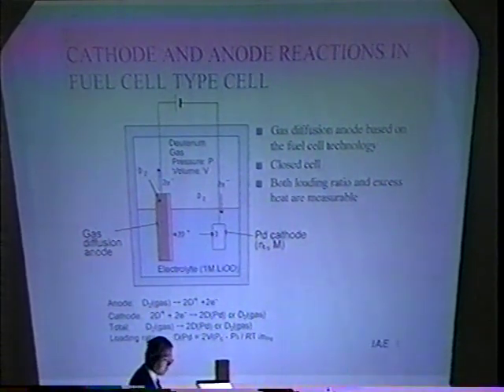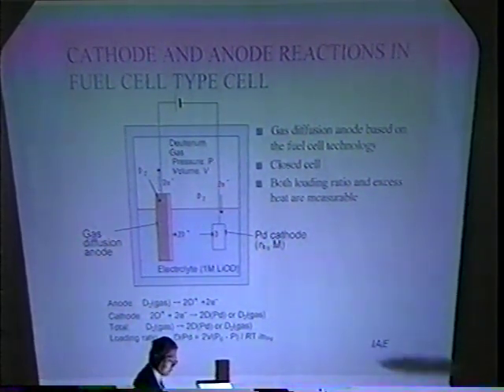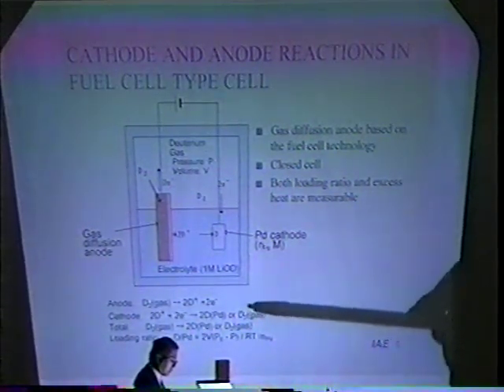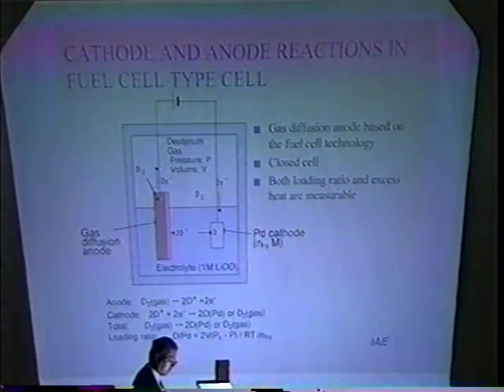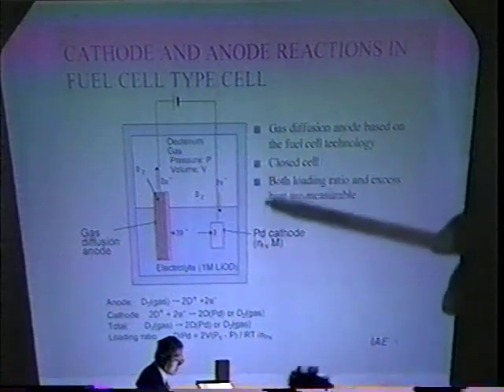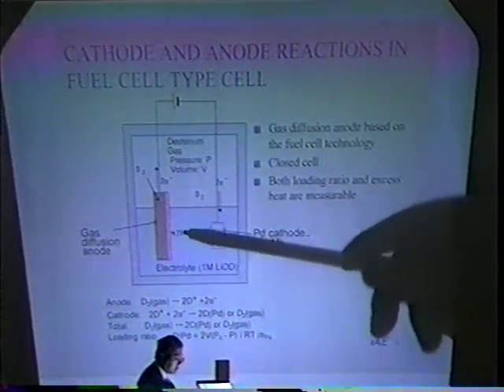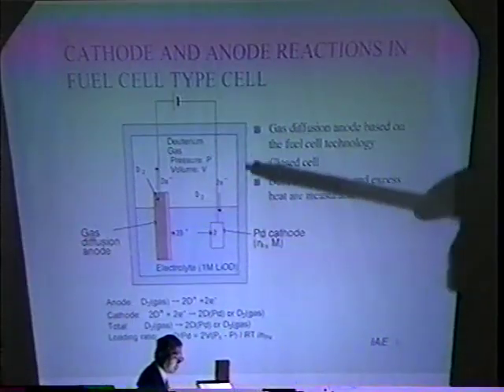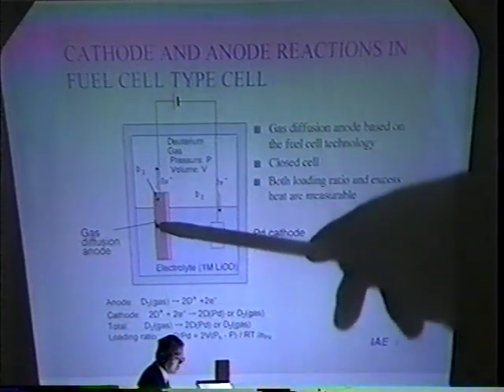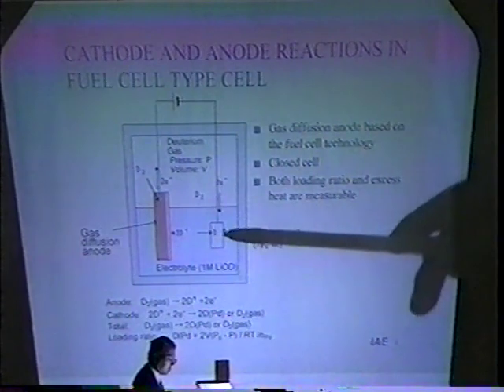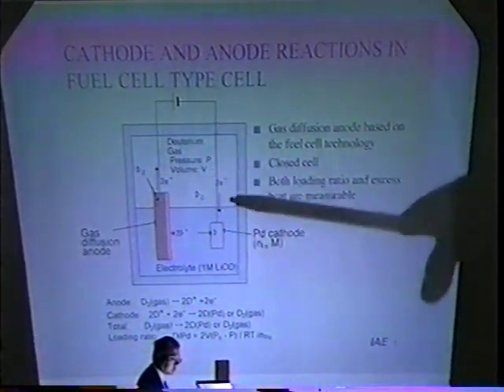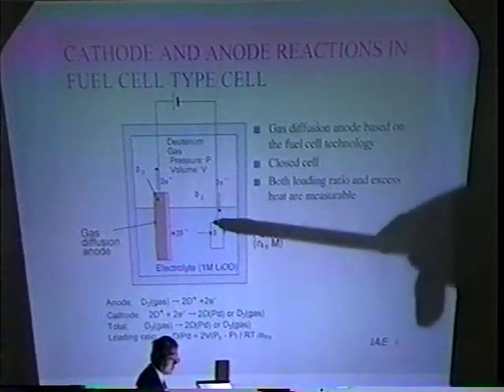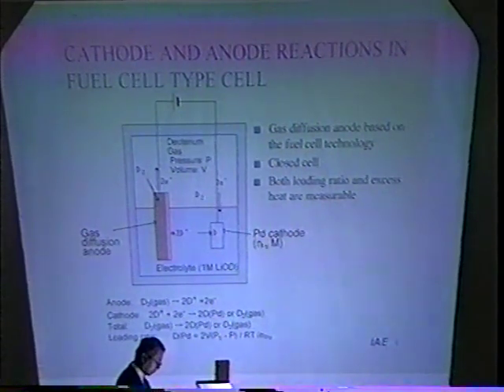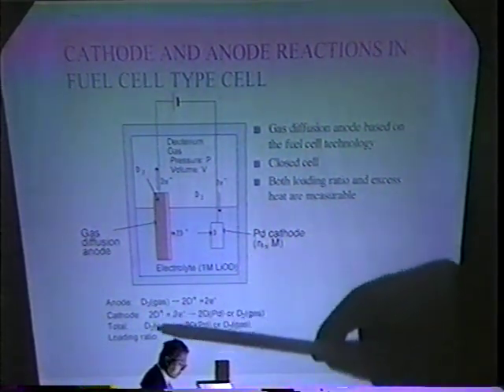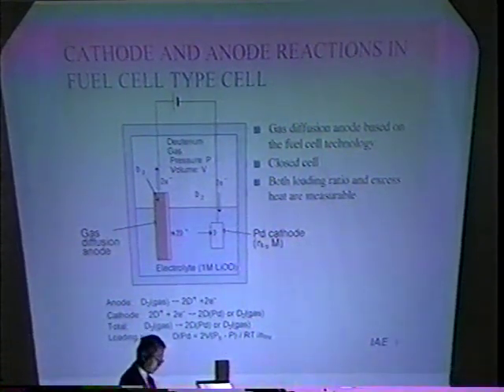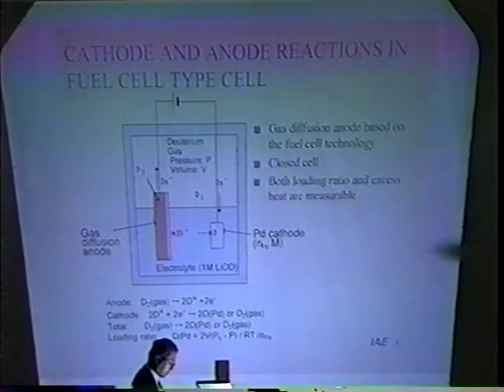This is a schematic of the anode and cathode reactions in the cell, these expressions respectively. The anode does not generate oxygen gas because the deuterium gas diffuses into the anode. And the palladium cathode generates deuterium gas, and the load itself is deuterium. And in this closed cell, the loading ratio can be estimated by this expression using measured pressure of deuterium gas and temperature.